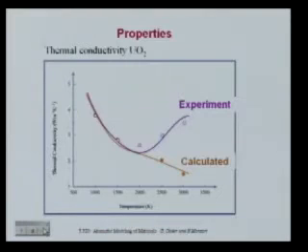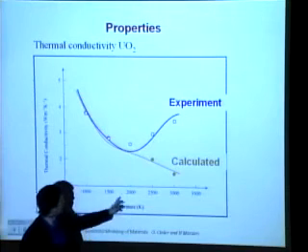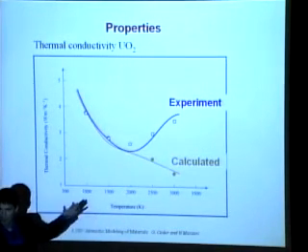And I'll tell you how they calculate this. They calculate this literally by doing a molecular dynamics simulation, looking at essentially energy transport through phonons. And thermal resistance is caused by phonon scattering. You have a phonon going through, and at some point that wave packet needs to become decoherent, get scattered so it can deliver its energy. Okay? But essentially, at least some form of heat conduction comes from phonon transport. And that's what the calculation, the brown curve, is. And then the purple curve is the experiment. And you see something kind of odd here. There's obviously a whole region of temperature with really good agreement. If I'd written a paper, I'd show just that part.